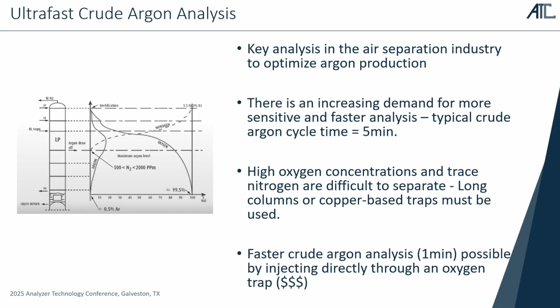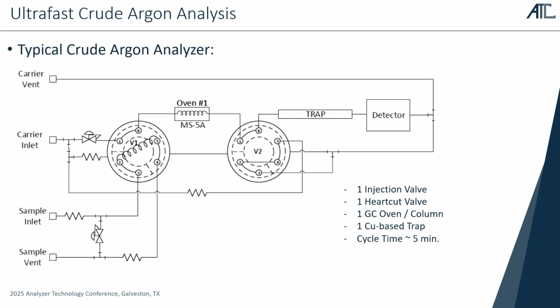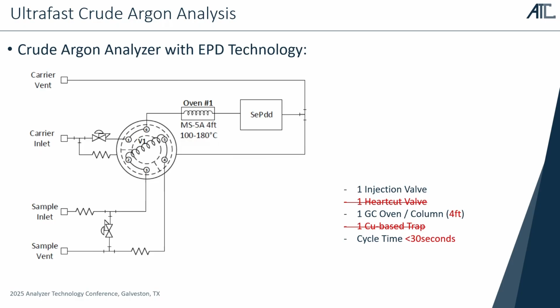Another key application that we developed would be crude argon analysis. I'm not going into all the detail, but it's a very important application in the field of air separation for improving argon recovery. And it's the measurement of trace nitrogen in a mixture of argon and oxygen. And typically, you would have a setup like this one with a long GC column and even an oxygen trap, because it can be quite difficult to separate trace nitrogen from oxygen. But thanks to the fact that we can measure and combine multiple wavelengths, we can do what we call spectral compensation, and therefore make a simpler system with a short GC column and only the detector at the end. So we can remove one column and one valve to have a faster analysis for the crude argon analyzer.